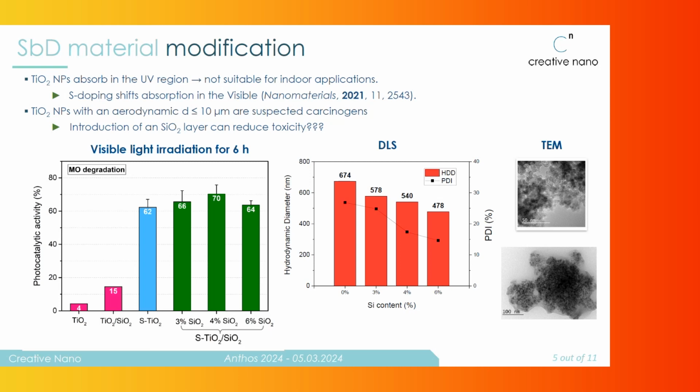And then we decided to apply a very simple safe-by-design approach to potentially reduce their toxicity. That is the introduction of a thin silica layer surrounding the titanium dioxide nanoparticle core at three different levels of modification. So this is actually adding 3, 4, or 6% content silica surrounding the titanium oxide nanoparticles. We were very happy to see that the activity actually increased, albeit slightly, but increased. It moved to 66, then 70%, and then partially dropped.